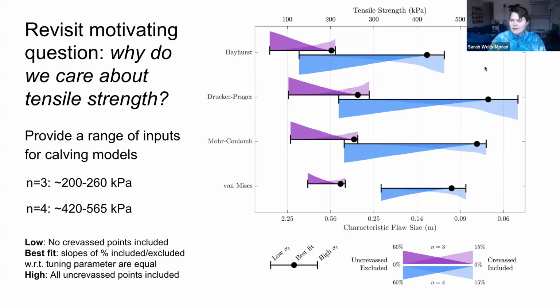So this full range over here is what we predicted for n equals 3 in purple and n equals 4 in blue. It is worth noting that the low range estimates of tensile strength are likely not to be the most accurate because of the previously mentioned crevasse advection. The low estimate was defined by no crevasse points included in the yield criteria. And so if some of the crevasse points still had managed to advect downstream, out of the stress state of formation, the low estimate is not likely to be as representative of stress states. And that shows in that the best fit estimate and the high estimates are close to each other in every single case.